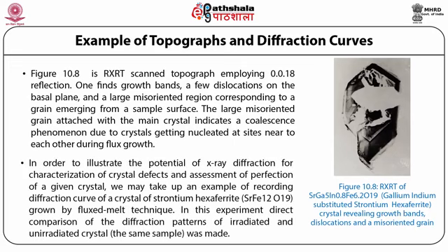In order to illustrate the potential of X-ray diffraction for characterization of crystal defects and assessment of perfection of a given crystal, we may take up an example of a recording diffraction curve of a crystal of strontium hexaferrite whose chemical composition is SrFe12O19 grown by fluxed melt technique. In this experiment, direct comparison of the diffraction patterns of irradiated and unirradiated crystal of the same sample was made.